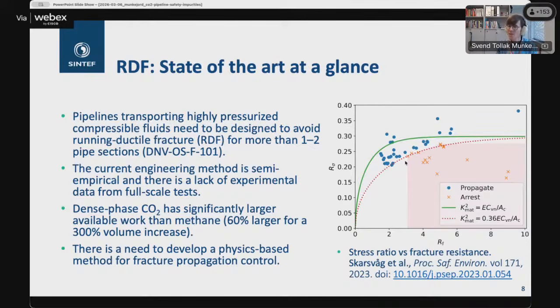And in particular, when making this plot, you put in the measured pressure, but when engineers want to evaluate a new design, they typically put in the equilibrium pressure, the boiling pressure, and they are not the same. And in addition, this method assumes that it is only the pressure at the crack tip that decides, and that's also a strong simplification. So there is a need to develop a physics-based method for fracture propagation control.